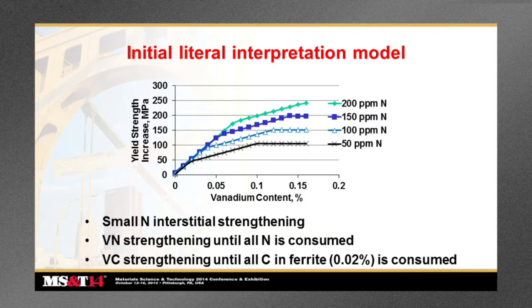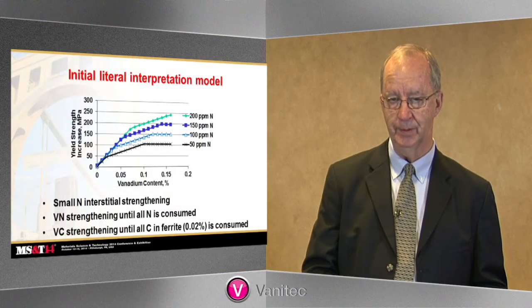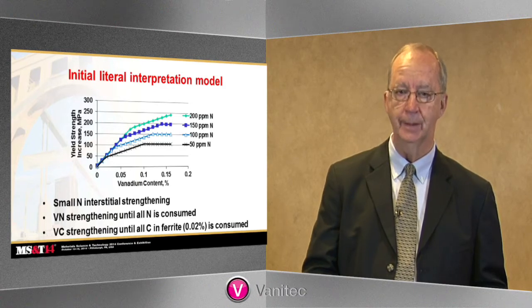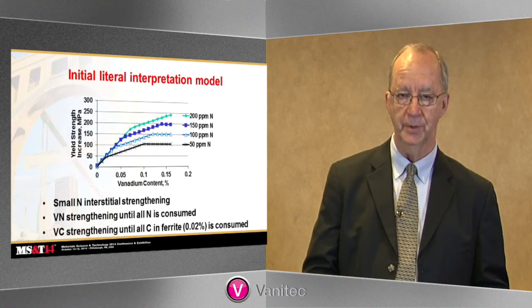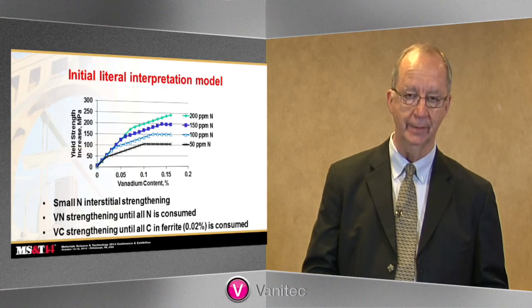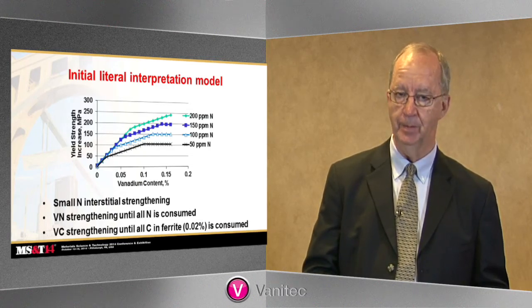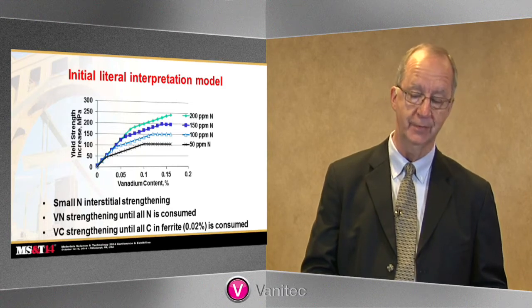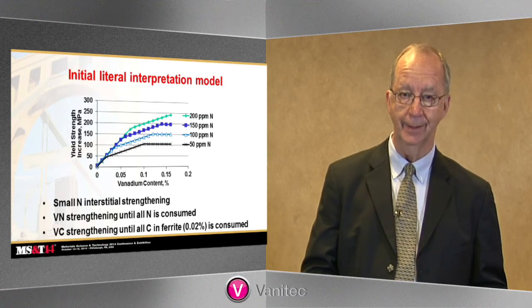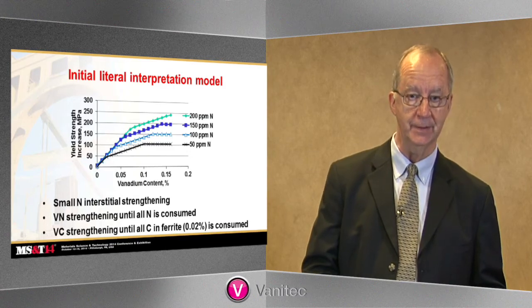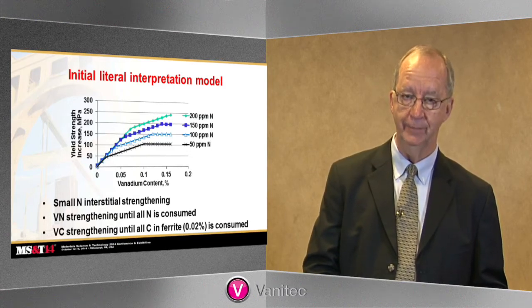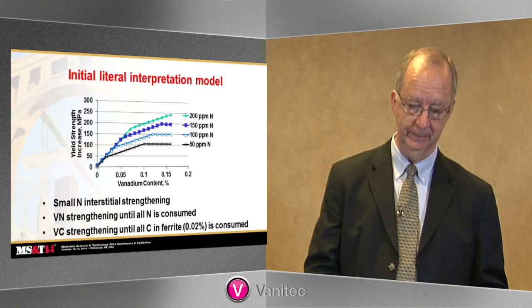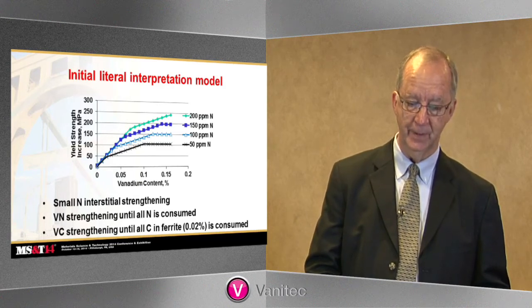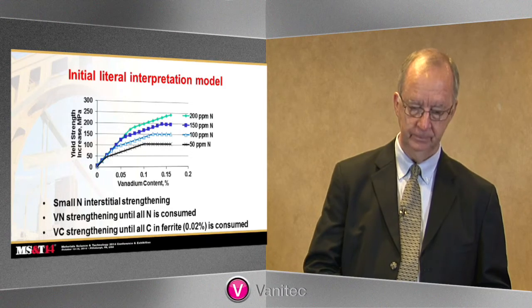Now, there can be many different carbon levels of steel that you can use this system with, but we have to remember that it's only the carbon in the ferrite that will precipitate and give you vanadium carbide strengthening. Precipitation of vanadium carbide in the austenite, if it happens, which is not particularly likely anyway because of the high solubility of vanadium carbide, would not contribute to strengthening even if it did. So you have the first slope, which is vanadium nitride strengthening.